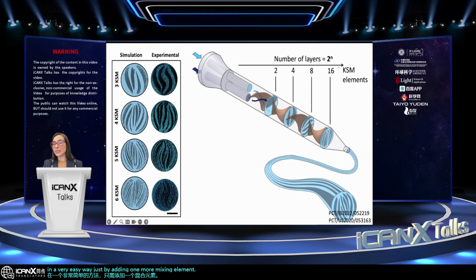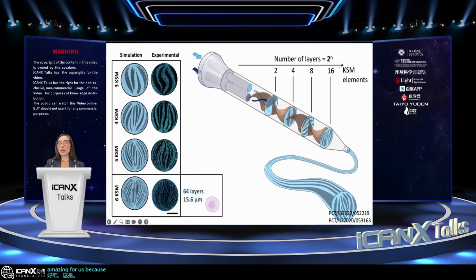And well, this is amazing for us because, for example, if you are using living cells, the mammalian cells are around 10 microns in diameter. So if we use this configuration of the Kenics static mixer with 6 mixing elements, you will have 64 layers inside your construct, inside a filament of 1 millimeter diameter, and with lines of single cell width. And this is amazing because so far the extrusion technologies of bioprinting out there cannot reach this resolution.